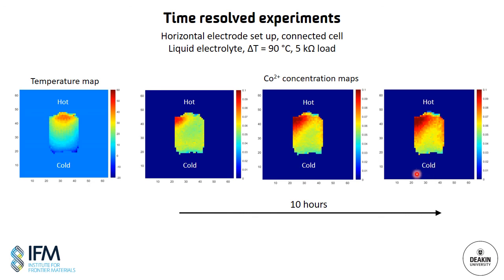And this is due to the lack of convection, meaning that the cell is relying on the far slower diffusion process to ferry those redox species between the electrodes. And this process does correlate also with a continuous slow reduction in the power being drawn from the cell.